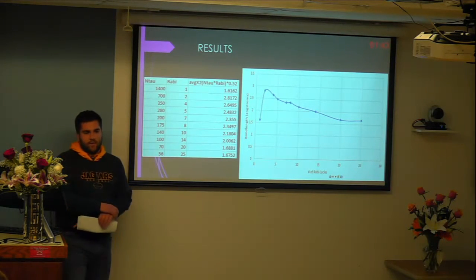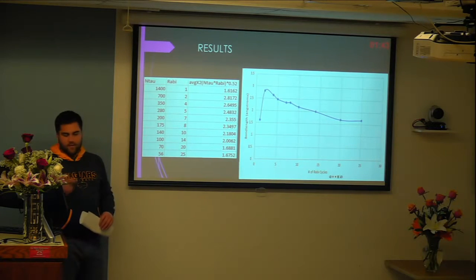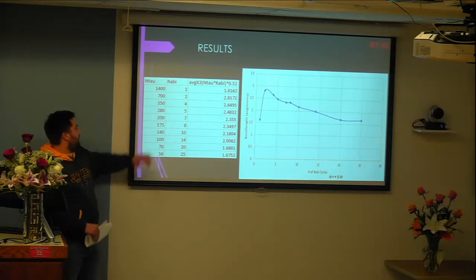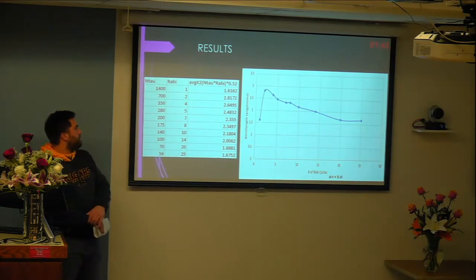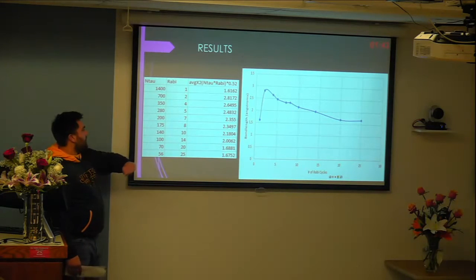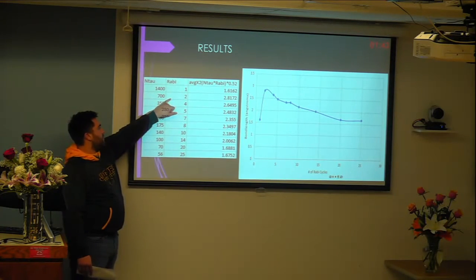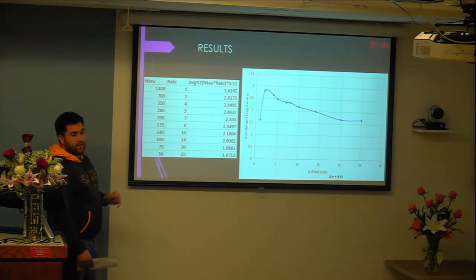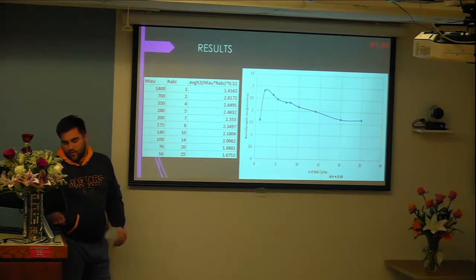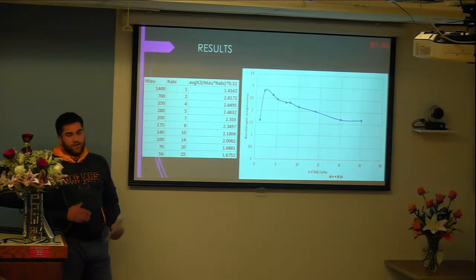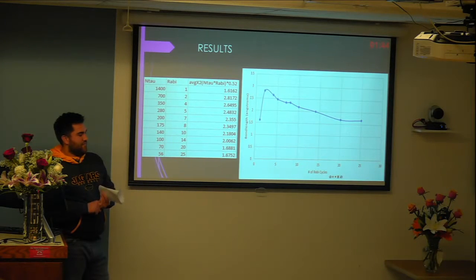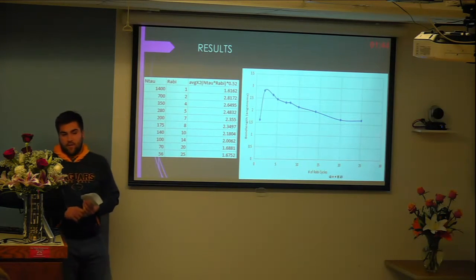Results. So I used 10 different experiments, and the n-tau to Rabi ratio is 1400. I try to keep that throughout the entire section here. And then this is the average bond length in angstroms. I also have a graph over there. The most success was with our UV laser being set to 2, and our time steps set to 700. It produces our largest bond length, and then assuming that it has the highest probability of dissociating, just breaking the Si-Si bond and starting to form a polymer.